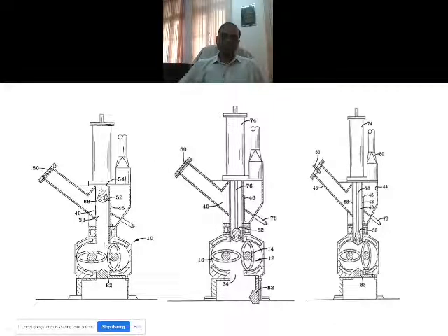But this pressure is applied while the rotor is rotating. You can imagine when the material is pushed in, because of the rotation, the material will tend to go up if there is a space. So you need to close it down. And the pressure is applied such that when there is too little pressure, this material will jerk here, the ram. But if you apply too much pressure, it doesn't move at all. It is completely hard, rock-like. That also is not recommended. A very minor movement up and down is permitted, and that pressure is maintained here. Not too big, so that it doesn't move at all. Not too little, so that it jerks. So it will be a very smooth up and down movement for this, depending on the RPM here. So that pressure is maintained.